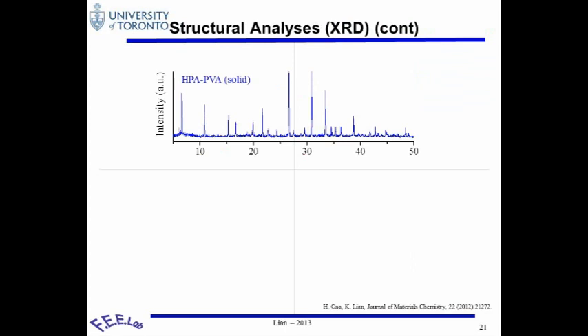And so we've done quite a bit of analysis by looking at these: the FTIR, the TGA, the DSC, and the XRD. We found XRD is a very useful tool for analysis of this material.